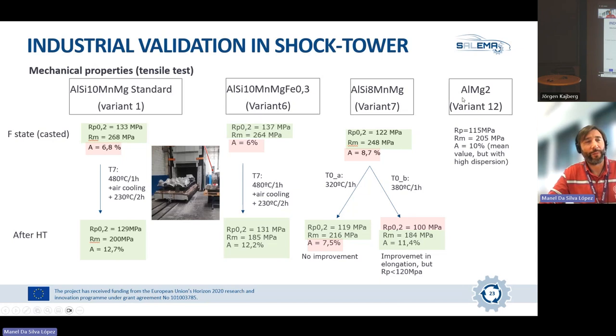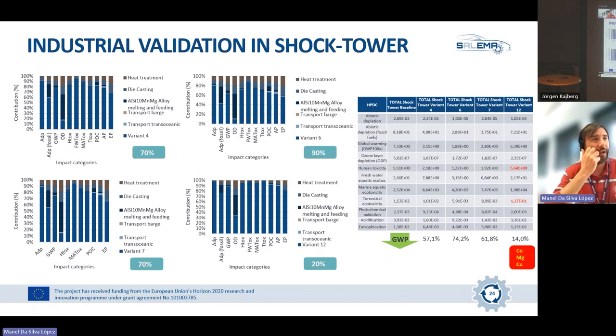And finally, regarding the aluminum magnesium 2 alloy that we tested, we had some issues regarding yield strength. In some regions of the shock tower, it was possible to almost reach all the requirements without heat treatment. But as I mentioned before, we had some hot tearing problems with this part, and with this complex shape a lot of cracking was observed, and there was a high dispersion, because if we tested a cracked part, of course, the mechanical properties went down a lot.